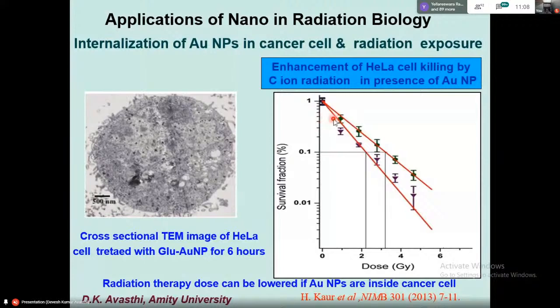So this curve is lowered down, and here you have the dose and the survival fraction. At 0 dose, both of them are 100% surviving, fine. At this point it is 0.1 survival, which means 10% are surviving and 90% are killed.